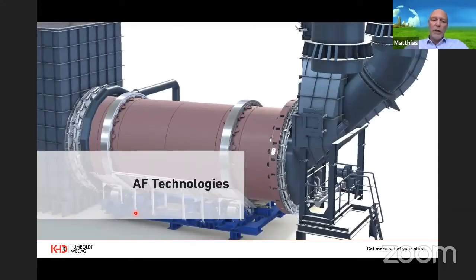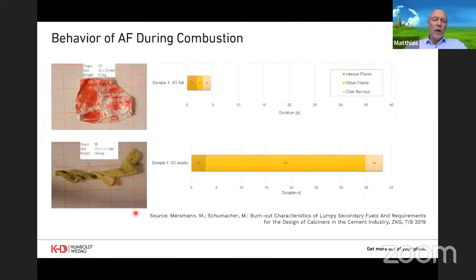Okay, my subject today, alternative fuel technologies. And why is that so critical? We tend to believe that alternative fuels are fuels, which is in a way true, but also not true, because these particles have never been fabricated to be used as fuels, which means they have properties which are not exactly ideal for combustion. This slide shows you, for example, one piece of plastic inside an RDF mixture that is rather small and rather thin, and this takes only less than 5 seconds to burn out completely.